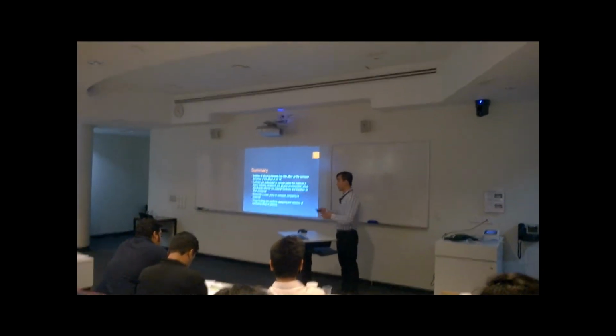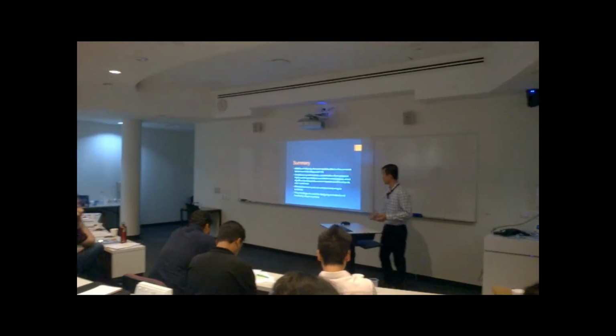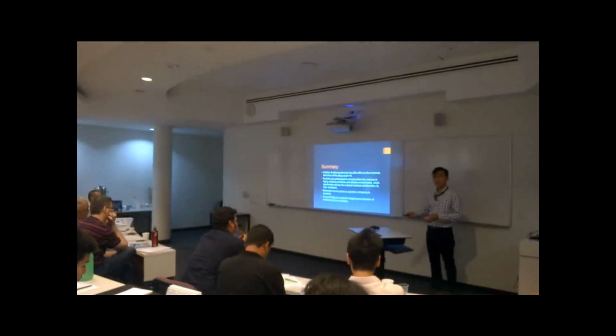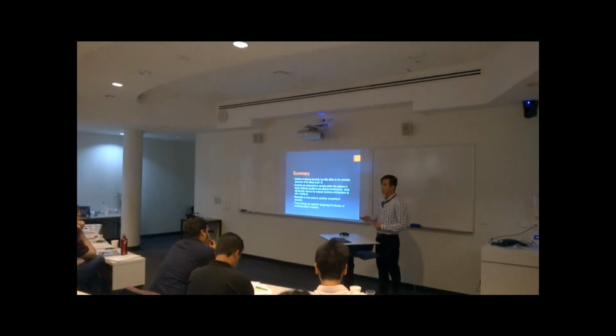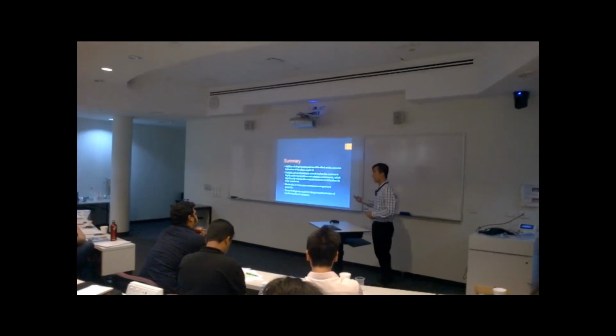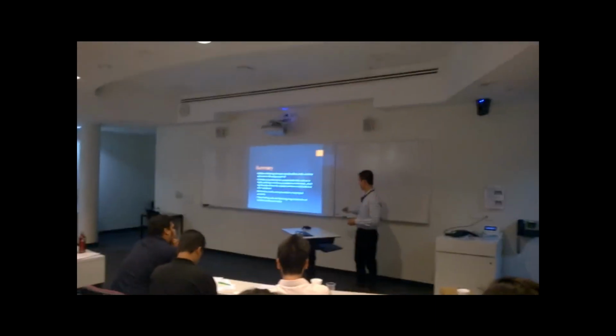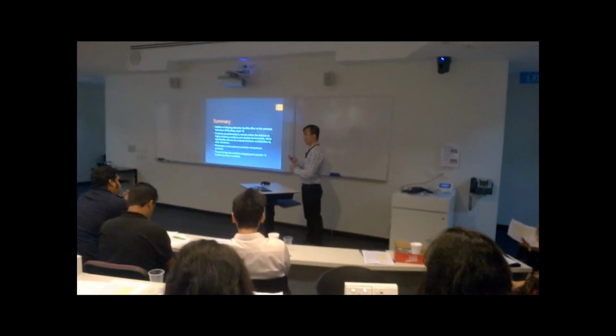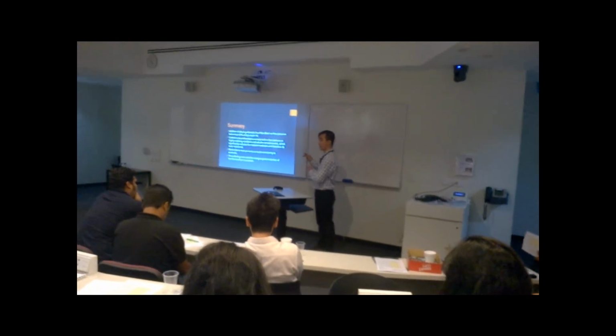Findings in my research. The first one is that the addition of different alloying elements to the alloys has little effect on the corrosion behavior in the solution. The ferrite matrix appears to be more prone to corrosion compared with the austenite matrix. And the most important finding is that carbide corrodes before the matrix in a highly oxidizing condition in an alkaline environment. This gives a very important point for the research to further discover the intent behind it, to increase the wear resistance of these materials.